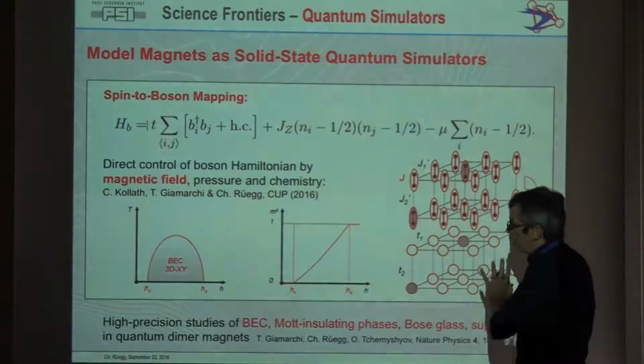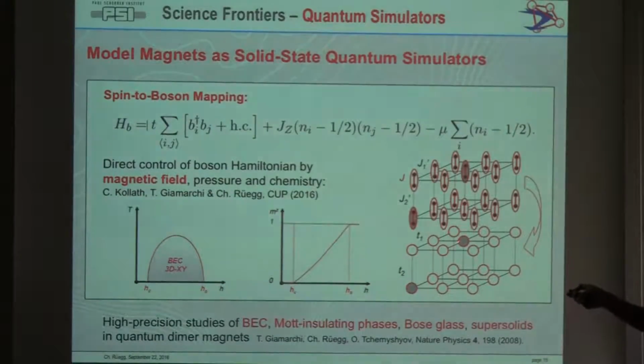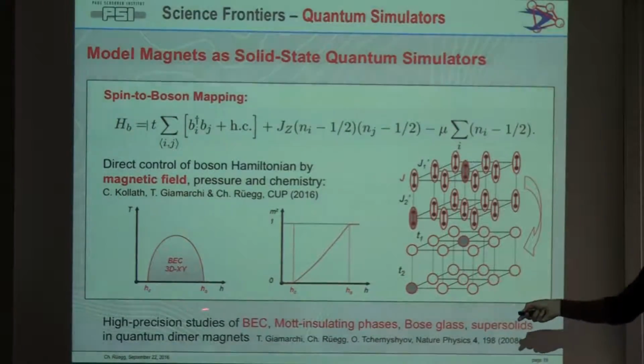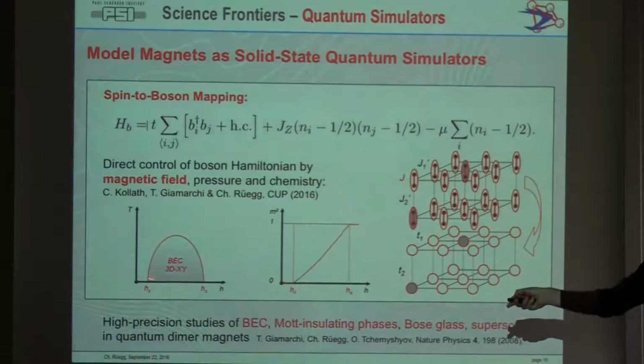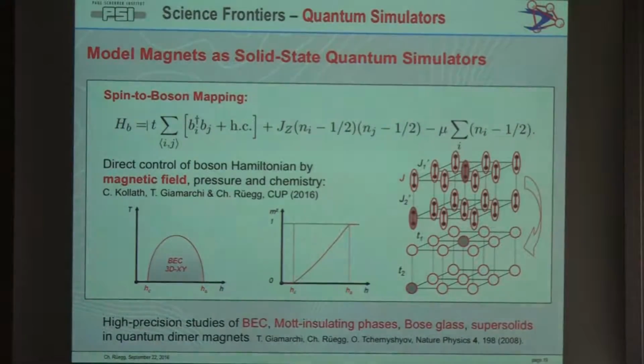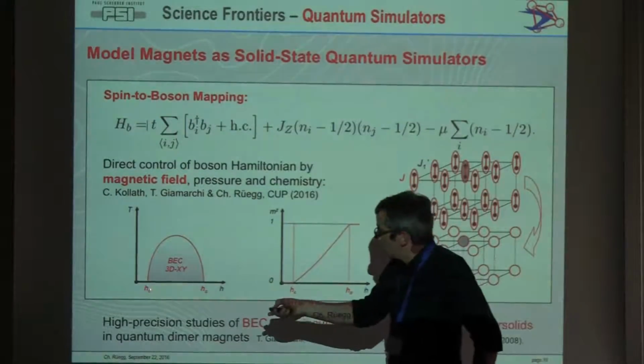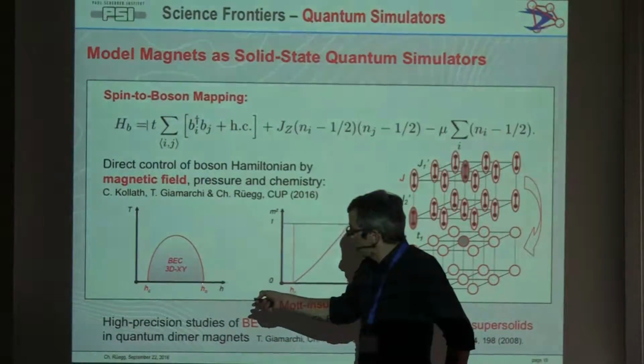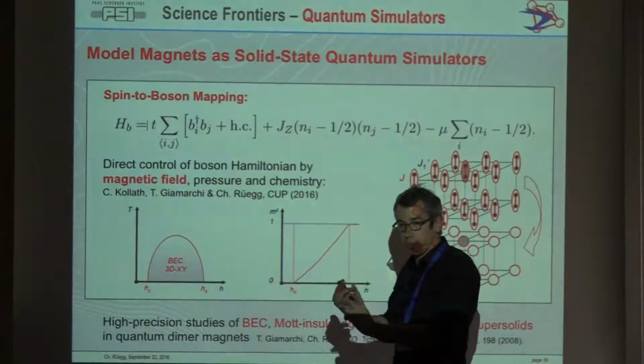I'll give you a bit of an overview in just a moment. So once you apply a magnetic field, first there is a spin gap, there's no particle present. Once you close the spin gap, the chemical potential goes down to 0. Then you start to populate the lattice with these triplet states, which can move around with hopping terms. And in this phase, you then get the condensation into a BEC, a 3D ordered phase at low temperatures. Again, the power here really is to control the densities of particles by having a critical field where the density is 0, and having the saturation field where every site would be occupied by a triplet.